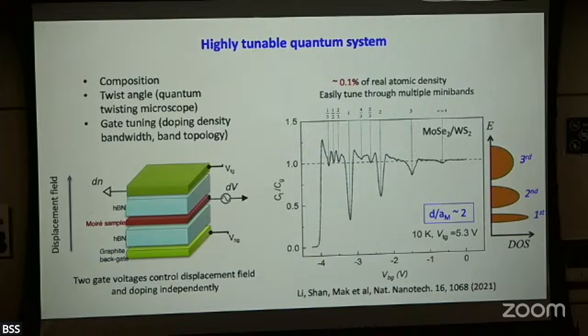Okay. That hBN layer in between is like their dielectric, yeah. But their thickness is chosen, or is also more... Yeah. So we can choose whatever thickness we want to use. So for example, this affected this background, so in this case, this d distance is about 2 times the Moiré distance. But if I make this d larger, then the background will be smaller. If you make d smaller, then the background will be bigger.